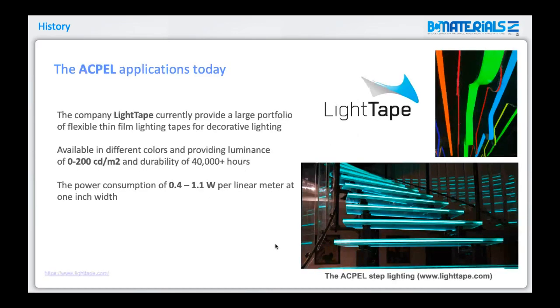So what is the AC powder electroluminescence today? I think the most recent developments are represented by the product portfolio of the company Light Tape, located in the United States. They are able to produce tapes which are thin film and flexible. They provide different colors and can reach up to 200 candelas per square meter, and durability extends to 40,000 hours at very low power consumption of 0.4 to 1.1 watt per linear meter at 1 inch width. So it's actually a very attractive technology, and